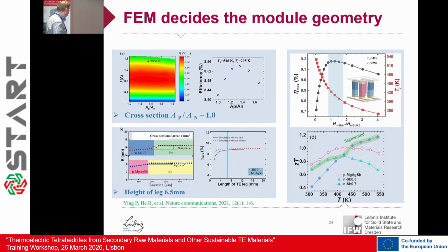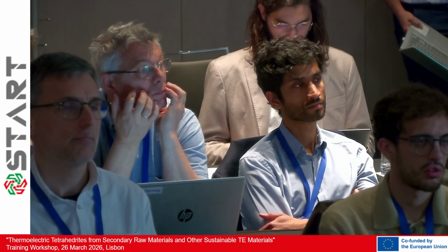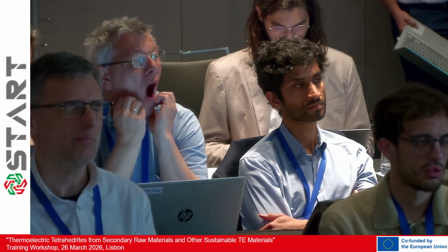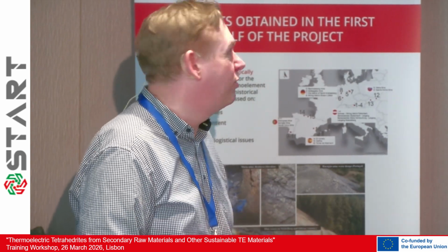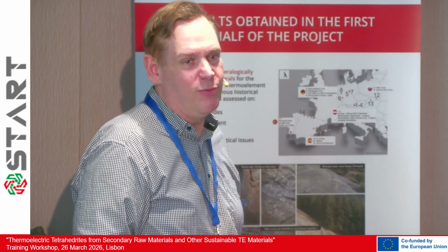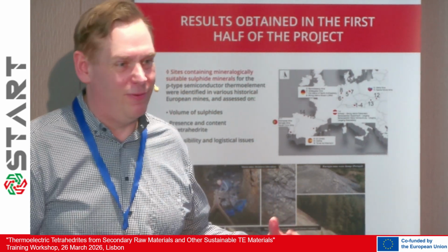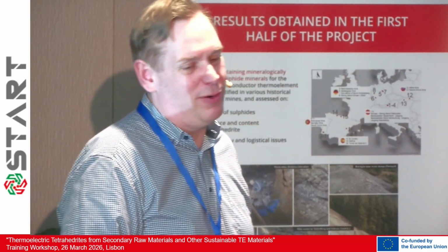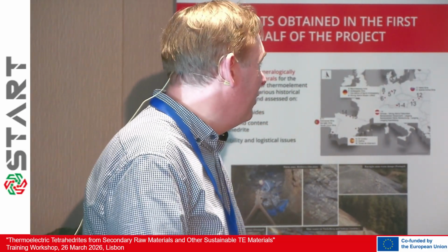Very important for all thermoelectric devices, and this also comes into play in these simulations, are in principle the contact resistances. I mean, you can have an excellent material, but if your contact resistance is high, then you ruin every device. On the other hand, you can also have a decent thermoelectric material, and if you have excellent contacts, you still get a good device. This is, I think, quite often overlooked when people talk about ZT; for devices, contact resistance is quite often more important to take a look at.